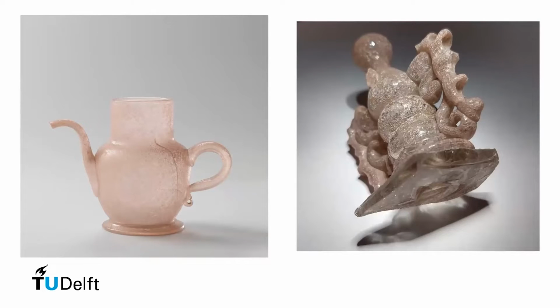And another important thing to realize is that even though people have said this looks pretty beautiful, it might, but it's very dangerous for the object because it may alter the structural integrity of the object. This little pot used to have a lid, but that completely disintegrated because of this crizzling process, and we can already see a crack forming here near the handle. So I'm a bit worried about this object, how long it will survive, even though it's kept fairly stable in the museum conservation studios. It is quite dangerous because the structural integrity also degrades during the chemical degradation.